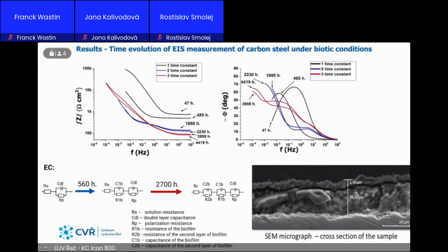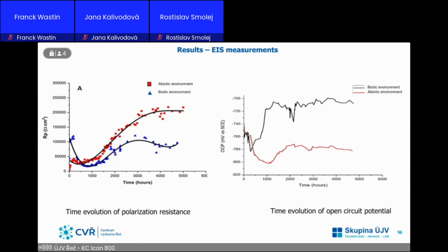We identify at the end of the experiment, as you can see on the SEM micrograph, that this time constant deals with 2 layers of biofilm on the surface. So, there you can see the polarization resistance and its time evolution. At the end of the experiment, you can see that under abiotic environment, the corrosion is higher, and so we see decreased corrosion rate by a microorganism. At the end it is by a factor of 2.